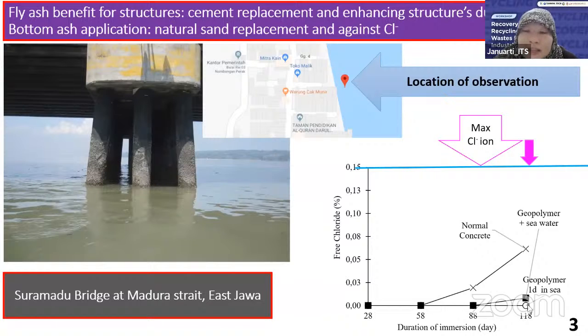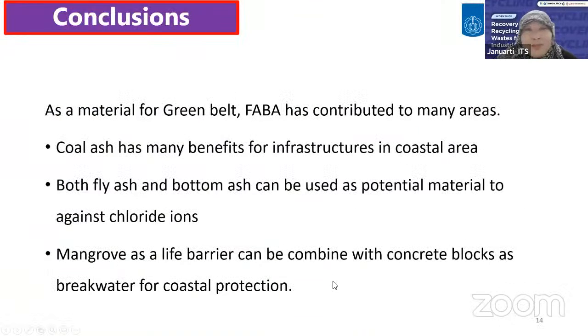And for the second specimen here, we cast our geopolymer, and one day after casting, we put it directly into the seawater. And what happened here? Again, the geopolymer can immobilize the free chloride ion very well. So this is the very big difference in durability between the normal concrete and the geopolymer. All right, then I come up with the conclusions because I was given very limited time.